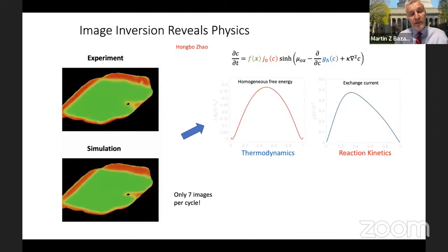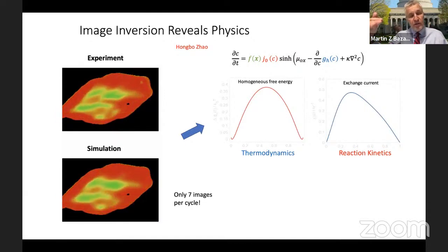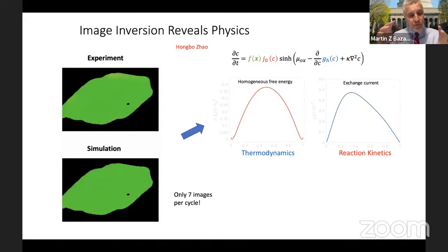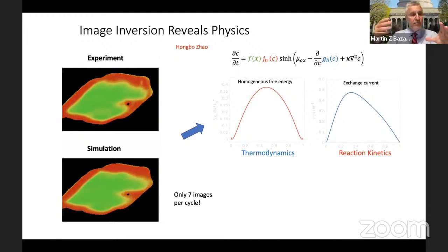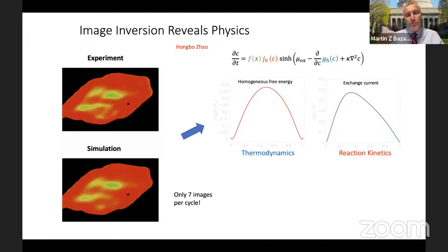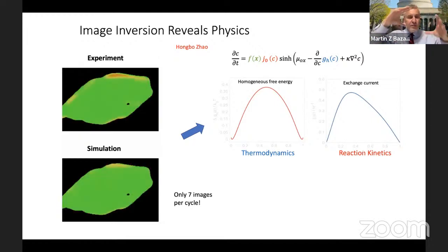So we don't learn that, partly because the experiment has error at the boundaries, and also because phase separation is highly degenerate. And if you don't give it some kind of guidance from sort of a template on the outside, then you can get sort of the right overall dynamics, but it won't precisely match because you essentially have to orient the phases, like nucleate them in the right way.